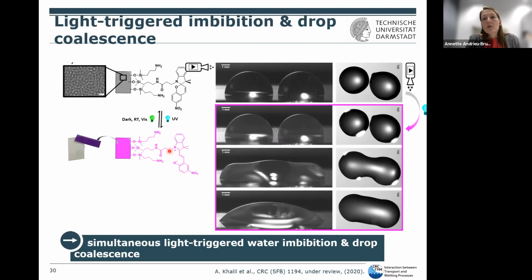And if now you choose the initial contact angle in this state such that this polarity change is sufficient, although small in contact angle change, but sufficient to go via this fluid exclusion, fluid imbibition transition, then we were hoping to somehow get droplet coalescence and fluid imbibition at the same time. And this is what you see in the images here as a side view and as a top view.